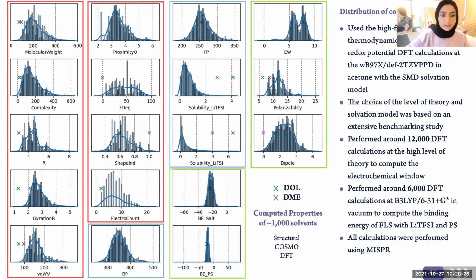As for the DFT calculations, we performed benchmarking studies in order to determine the level of theory and solvation model to use in order to make sure that we get accurate trends in the data. For example, for the electrochemical window, we used a very high fidelity functional and basis set, the omega functional here. And the total number of calculations summed to around 12,000 DFT calculations that were automatically handled using the MISPR infrastructure.